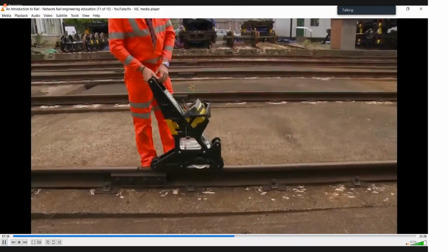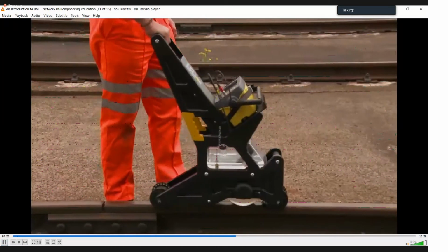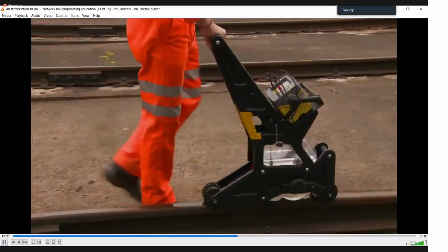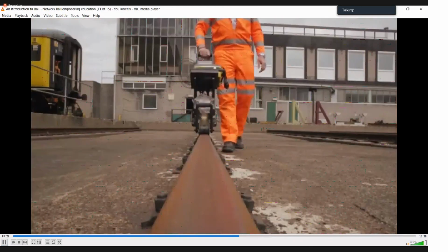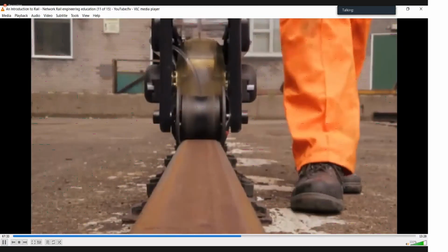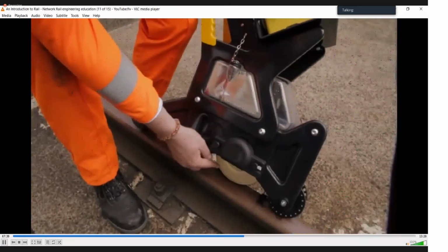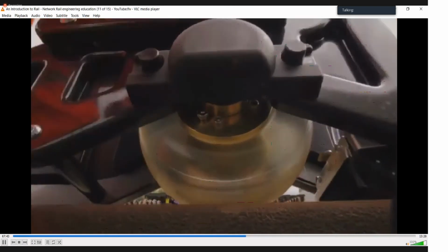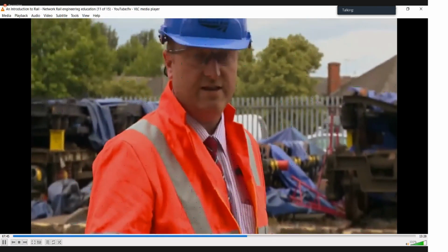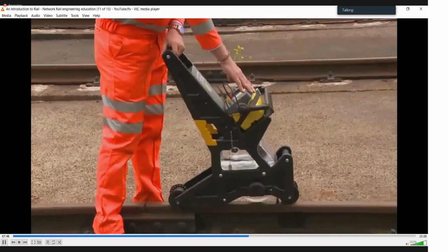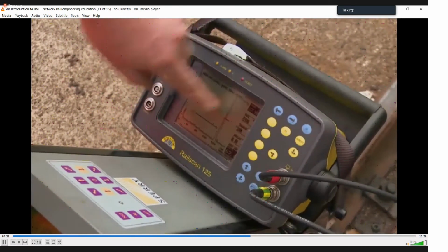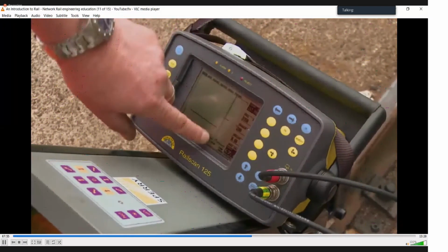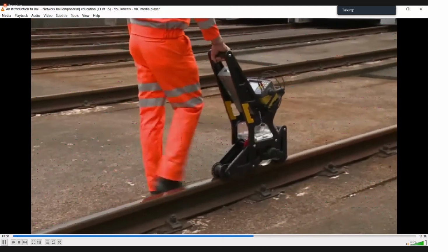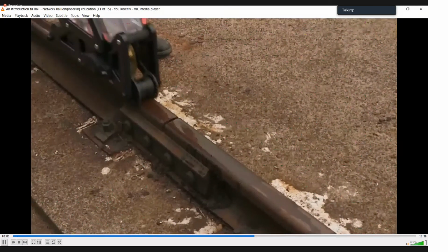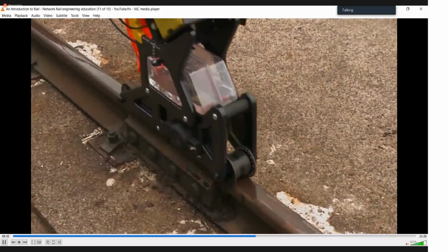This piece of equipment here is a Sperry roller search unit, also known as a walking stick. This is used by our ultrasonic operators who carry out a large amount of pedestrian testing in areas where we can't use vehicles to test, or in areas in lower category routes where we don't program the vehicles. The ultrasonic equipment here contains the Sperry roller search unit. This contains 9 probes which are used to scan the head and web of the rail. The flaw detector, which provides the signal and response, is used to detect any defects internally in the rail. This is contained in a walking stick to make it easy to push along the rail to ensure the stick stays aligned with the rail to carry out the necessary inspections.